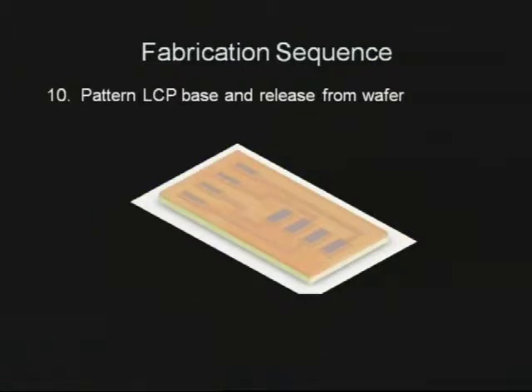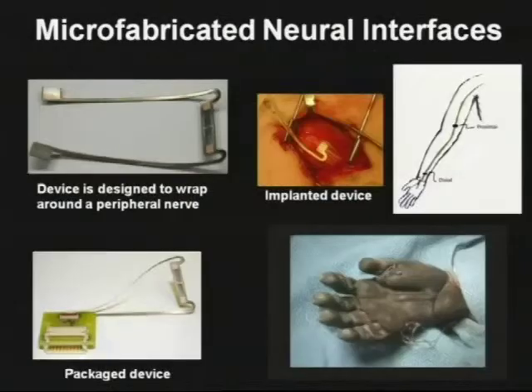LCP. I should mention here the LCP is not photodefinable. So in order to pattern the LCP, we use laser micromachining techniques. And we have a laser micromachining tool in our lab in the Glennan building. And that allows us then to literally cut out the unwanted LCP. And then we simply dip the wafer into acetone, which dissolves that adhering photoresist, allowing the device to be released.